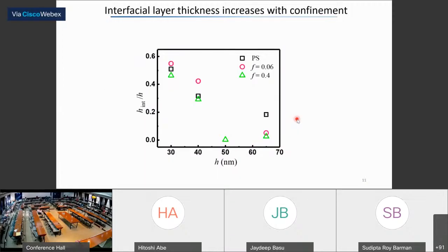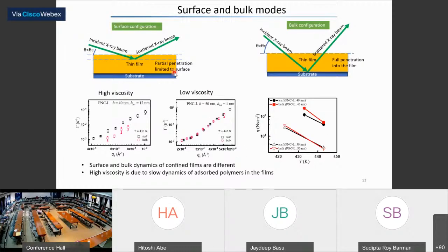And so if you look at interfacial layer thickness now, you see that it is increasing, of course in proportion to the thickness. So that is normalized to the total thickness, but definitely you see that this increases as you go to lower thickness, as we discussed earlier. Now, to specifically probe the role of this interfacial layer as well, we probed something whereby, by varying the incident angle, you are able to probe surface or interfacial modes, which are more surface confined, versus looking at dynamics which is coming more from within the film, because this interfacial adsorption of the film is happening near the substrate.